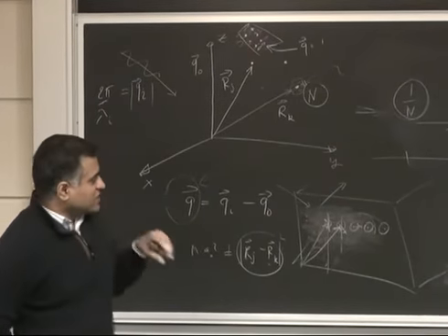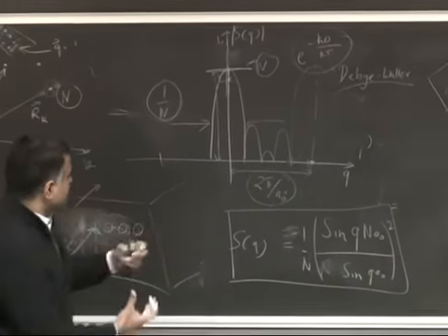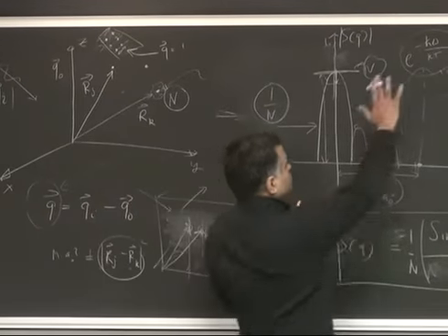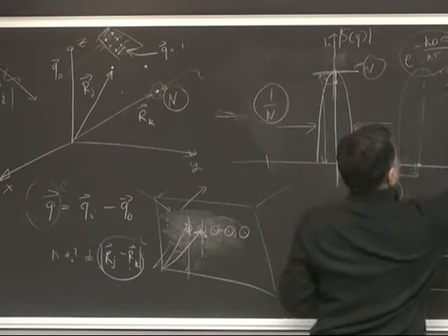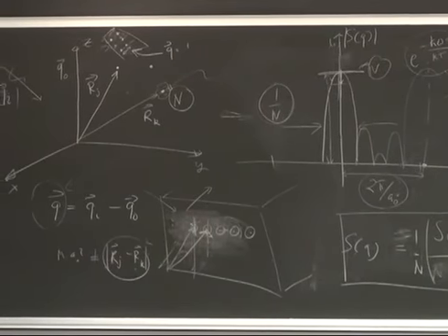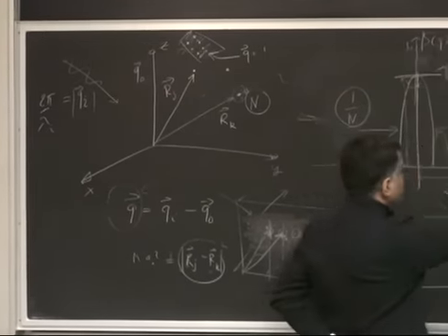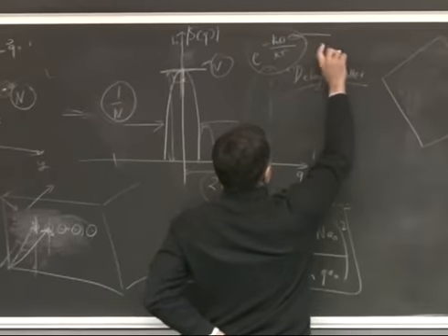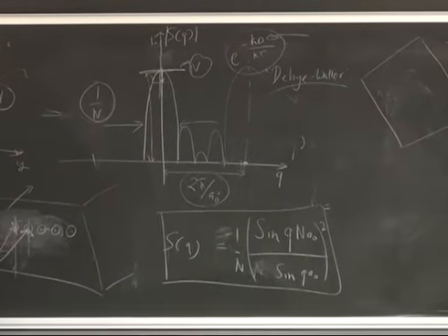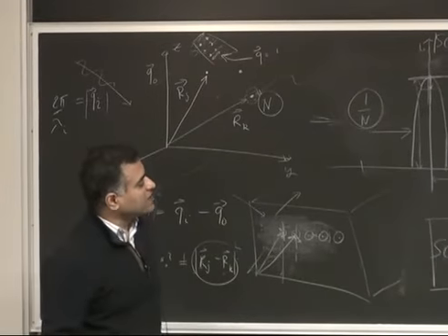So just to summarize again, the structure factor tells you of crystal structure. It tells you how many atoms are there, what's the crystallite size, the height of it, the width of it, and all that. And typically, just to look at these numbers, the phonon vibration energies of most solids. For silicon, for example, it's about 60 millielectron volts, and in gallium nitride, it would be about 90 millielectron volts. These are typical optical phonon vibration energies, and in that case, at room temperature, it's not a very strong decay, is what I'm saying. But if you start heating up to a few hundred degrees C, then you see this decay. So the Debye-Waller factor.